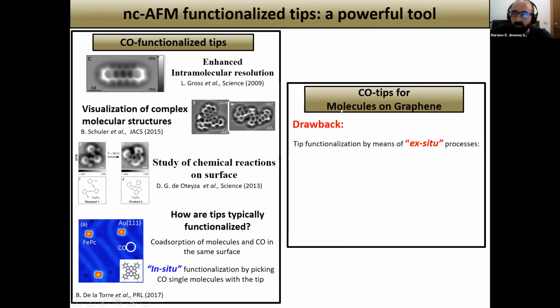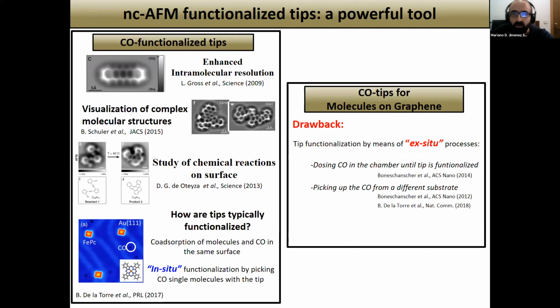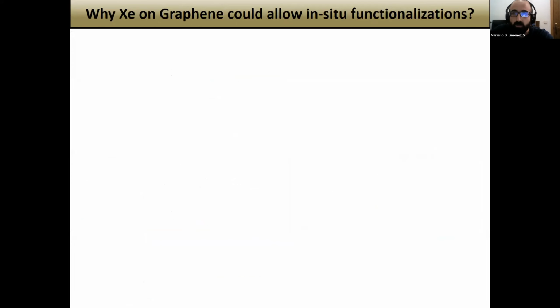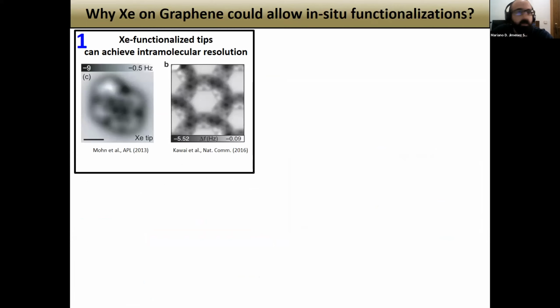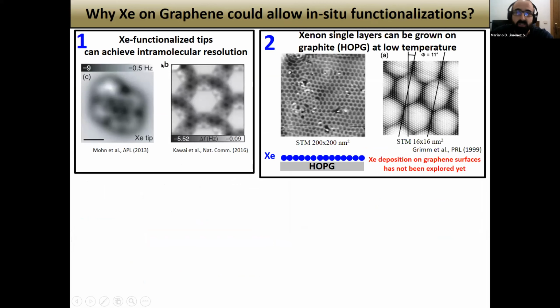There are some drawbacks, in that these functionalizations are typically performed by means of ex situ processes, like dosing CO in the chamber until a CO molecule is placed at the tip apex, or like picking up the CO from a different substrate. And here is where xenon enters. Xenon could be used to carry out in situ functionalization on graphene surfaces. And why? First of all, because a xenon functionalized tip can achieve intramolecular resolution. And second, because xenon has been deposited and visualized on graphite surfaces, which suggests that it could be possible to do it also on graphene. Nevertheless, it has not been explored yet.